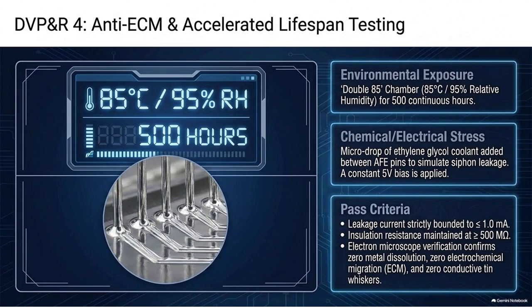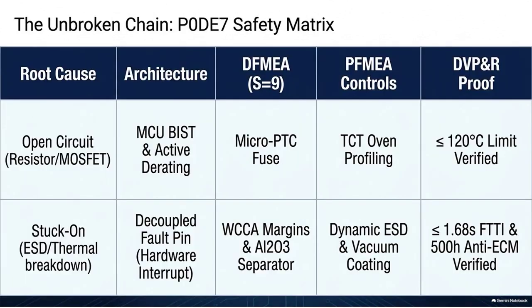And while the MCU is sweating under all that fake data, the engineers act like saboteurs. They inject a massive instantaneous 4.30-volt analog signal directly into the AFE chip. A simulated catastrophic overvoltage event with zero warning. And the hardware comparator has to spot it in microseconds, pull the physical fault pin low, while the software is simultaneously racing to filter the noise, confirm the voltage for the 1.68 seconds, and log the